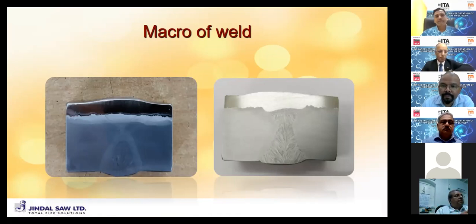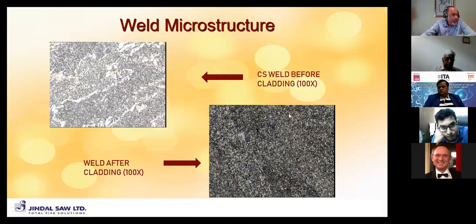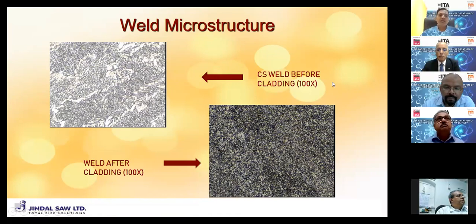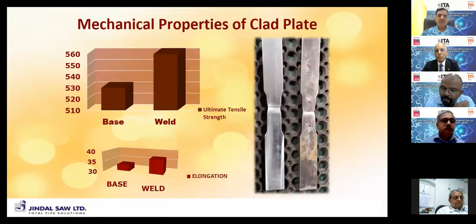Next slide, please. You can see here there is a difference. This is the weld microstructure before weld cladding. You can see the Widmanstätten ferrite and polygonal ferrite. But if you perform the electroslag welding, the weld is refined and you get a very fine microstructure. For mechanical properties, we have conducted the tensile test, which met the required properties.